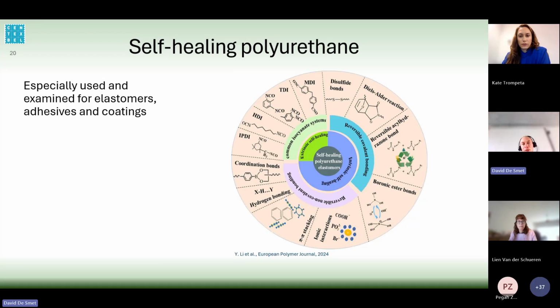This is actually not limited to one type of isocyanate. You can use aliphatic and aromatic ones. Of course, as Pia mentioned, this only allows a single repair. That's why we are looking into intrinsic healing, in which we use reversible bonds within the polyurethane. We can make a distinction between reversible covalent bonds and reversible non-covalent bonds. Ways of covalent bonding are disulfides, for instance, urethane bonds, imine bonds, etc. Those are reversible covalent bonds, which can be broken and reformed again.